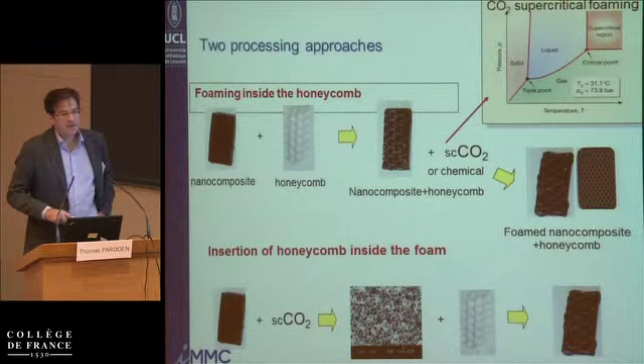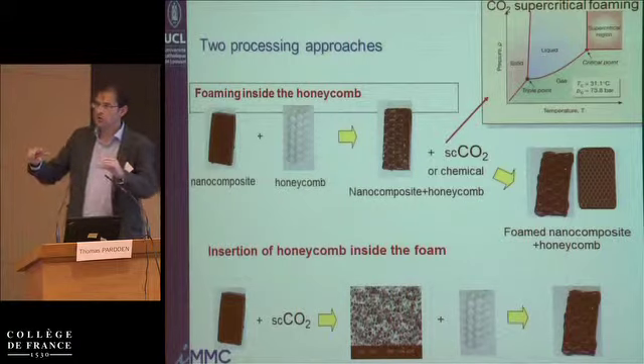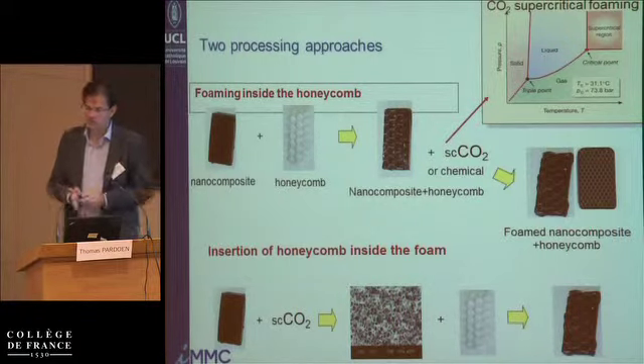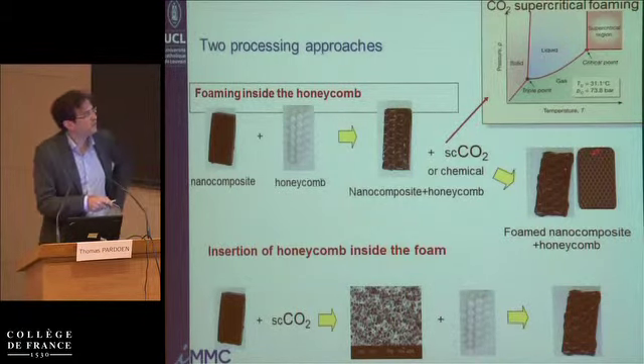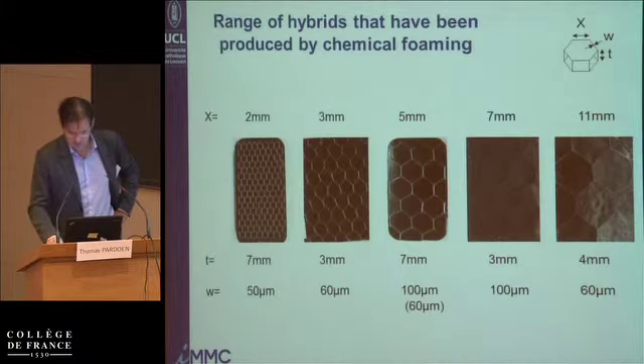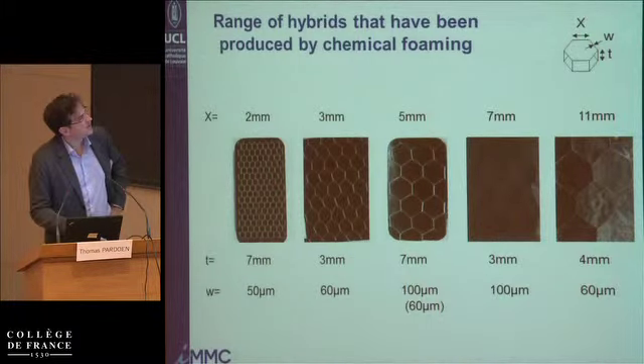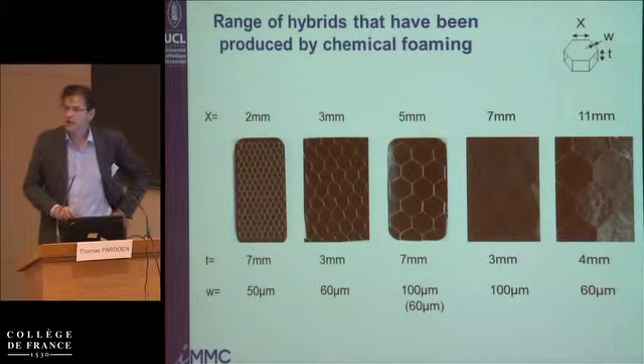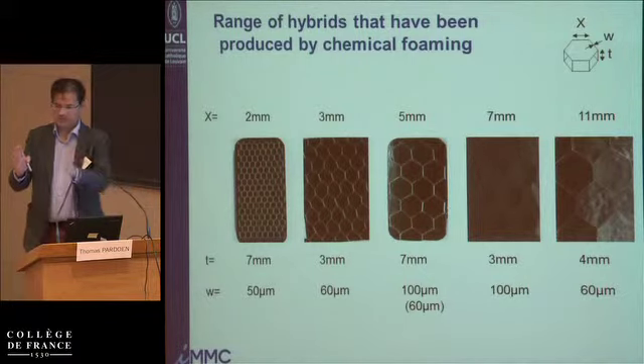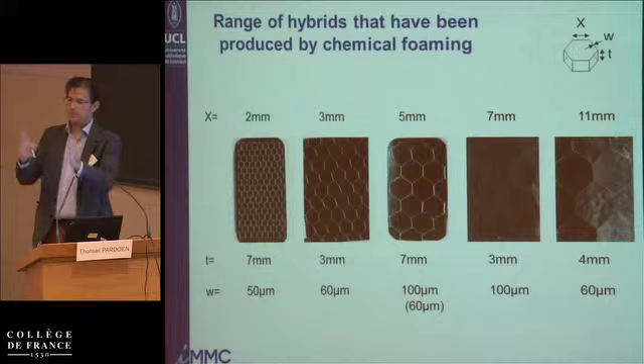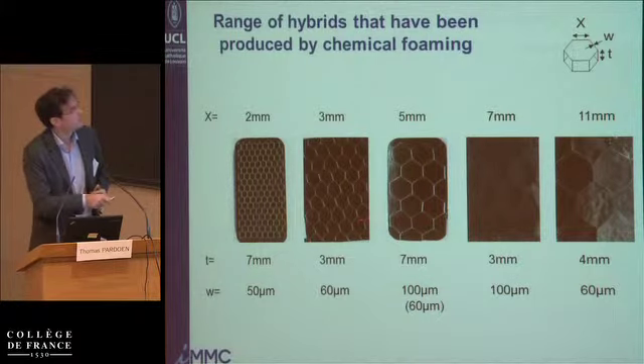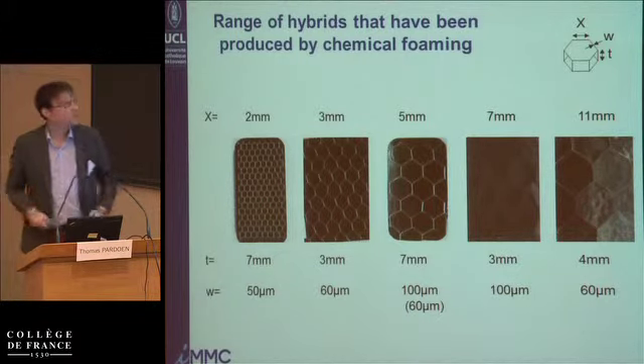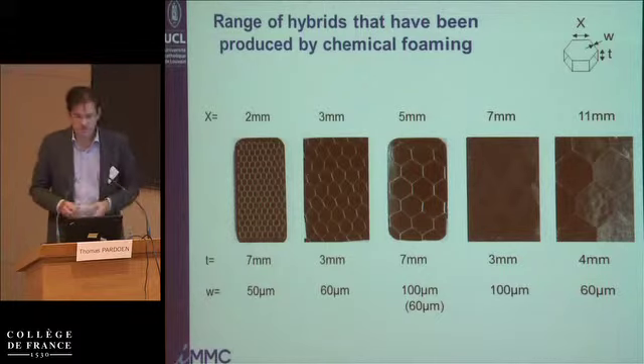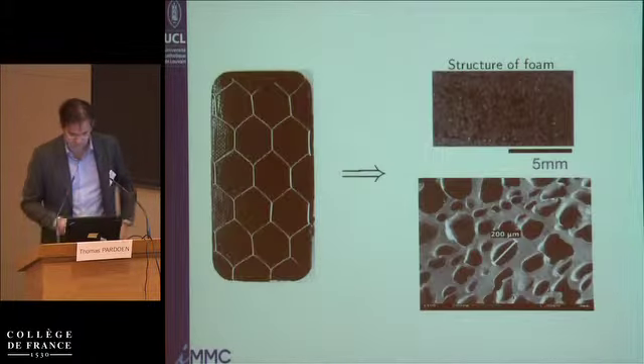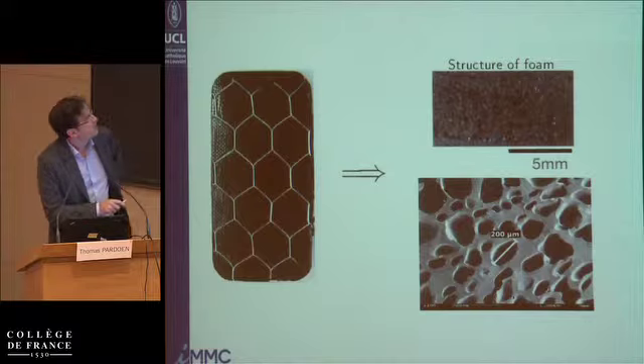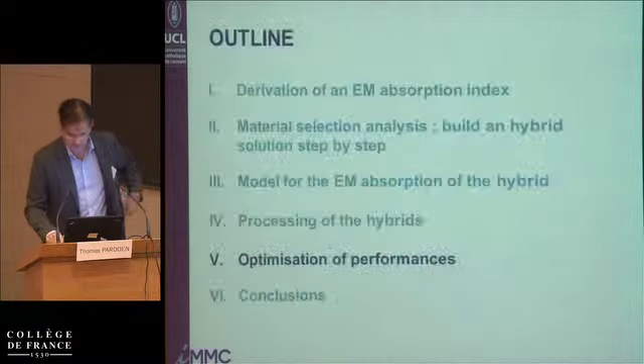The other approach is mechanical insertion. We make the foam, and then we press the foam inside the honeycomb. Our preferred method up to now is chemical foaming. And these are examples of material samples that have been produced. Right now, what Pierre is able to do is a square of 20 centimeters by 20 centimeters, which looks like this, so much wider. So different sizes, different thicknesses to play around. All right, so this is the multi-scale structure of the foam.